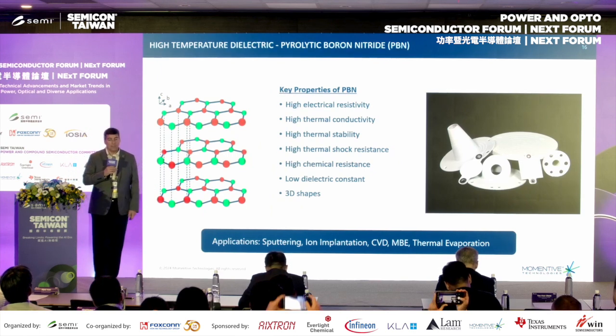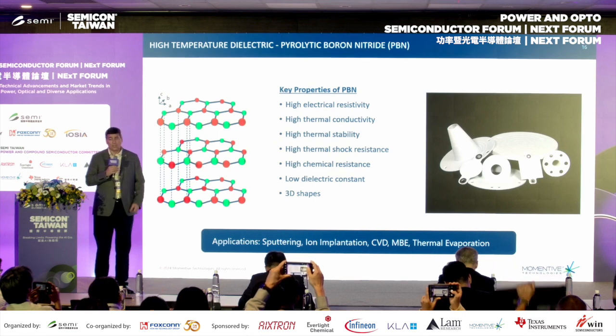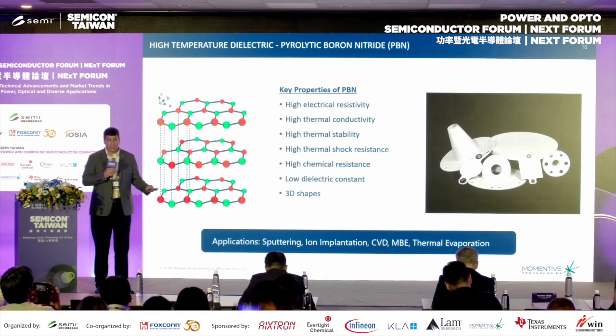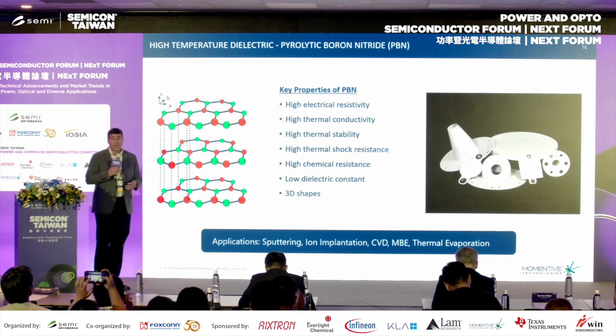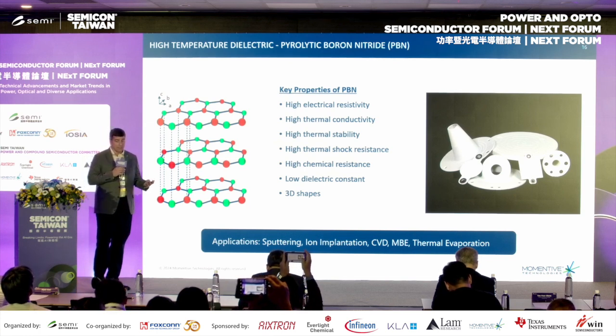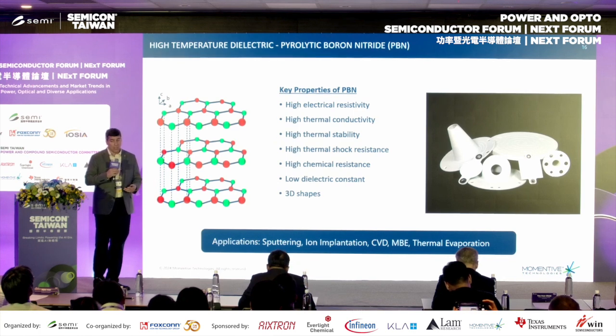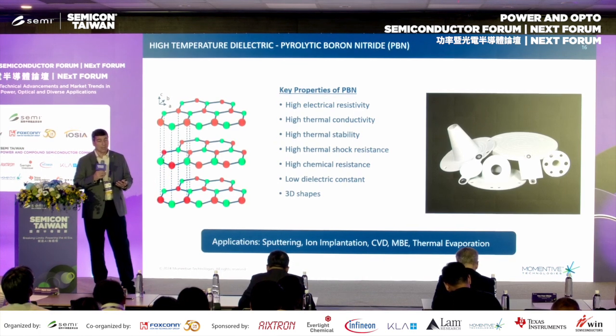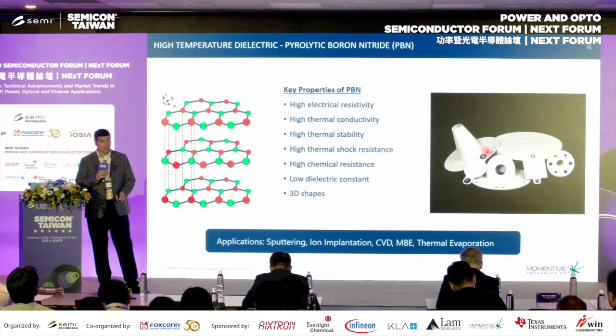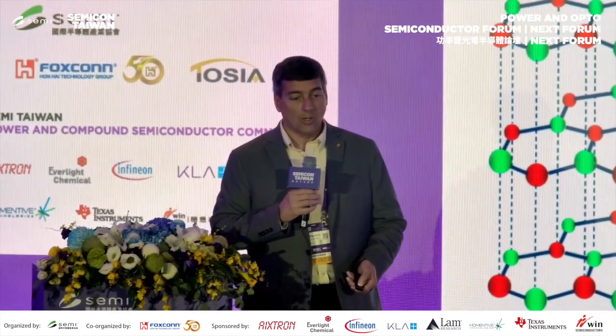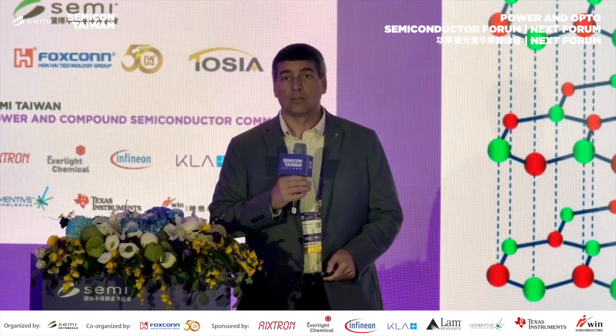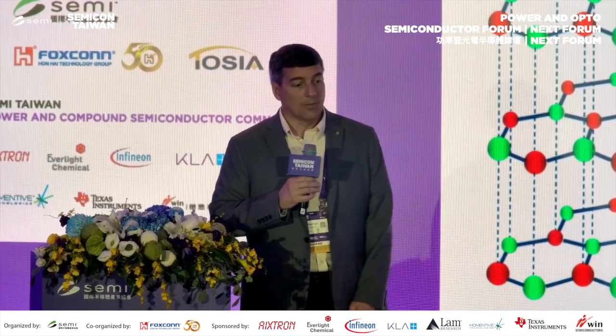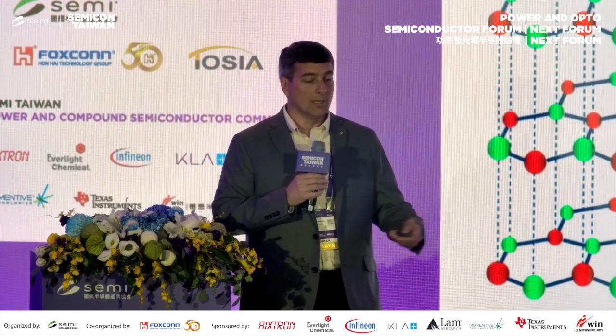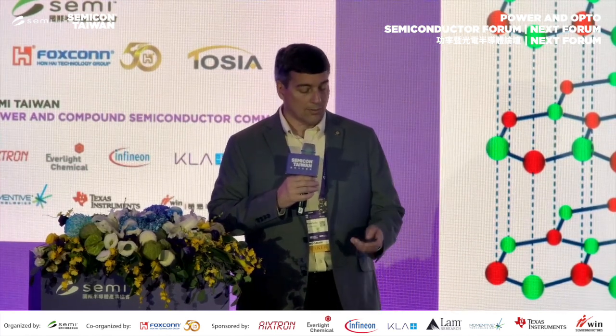So why PBN? It's got a lot of unique properties that make it really attractive for these types of applications. As I mentioned, it's got this very high but tailorable electrical resistivity. It also has very high thermal conductivity and very good thermal stability as well, which combine to give it very good thermal shock resistance and chemical resistance. It also ends up having a low dielectric constant, but because we do this process via CVD, you end up being able to make pretty much any shape of heater. These are all different heater forms that you can imagine, right? So fully three-dimensional. Obvious applications are in sputtering, ion implantation, CVD, MBE, thermal evaporation, lots of different options.